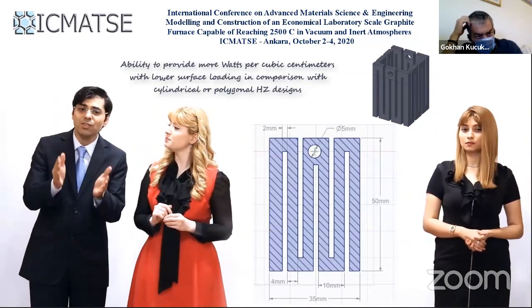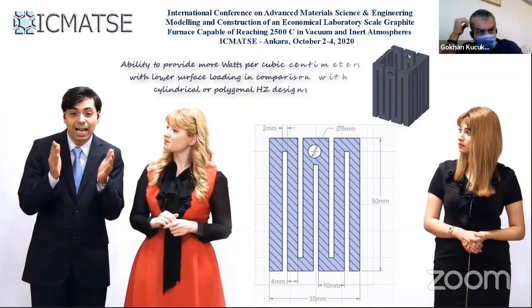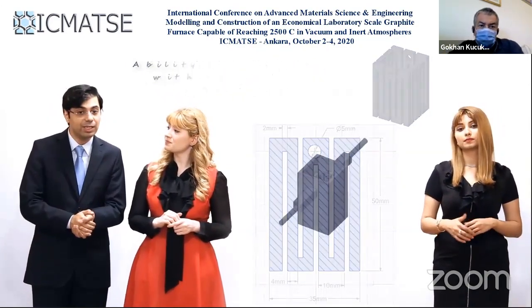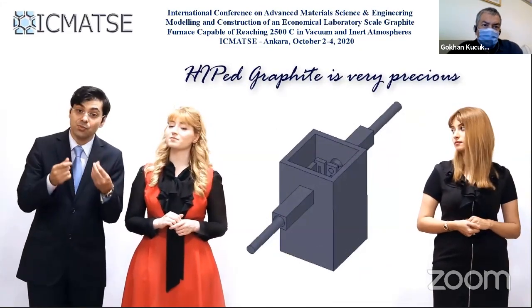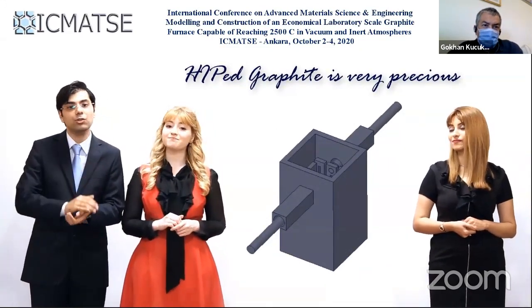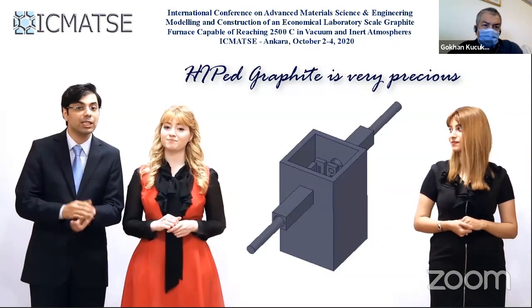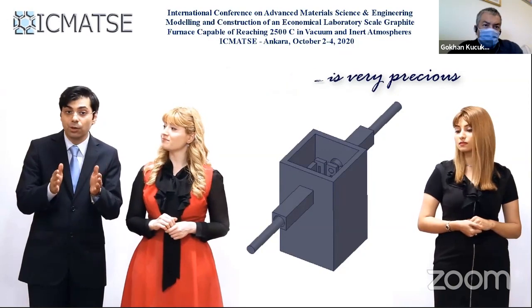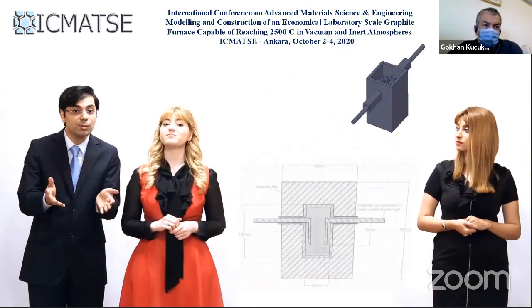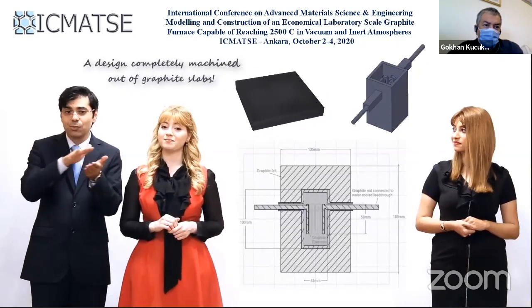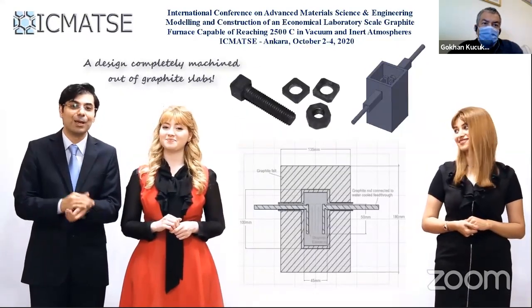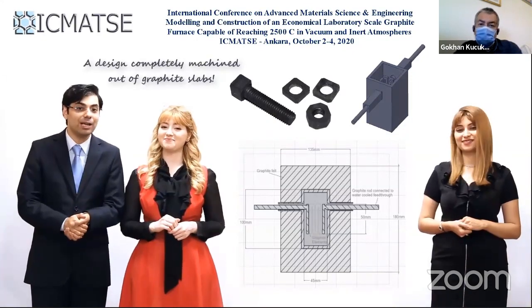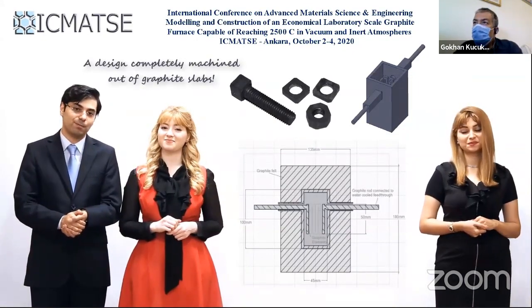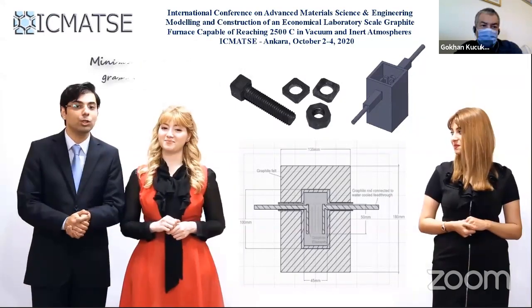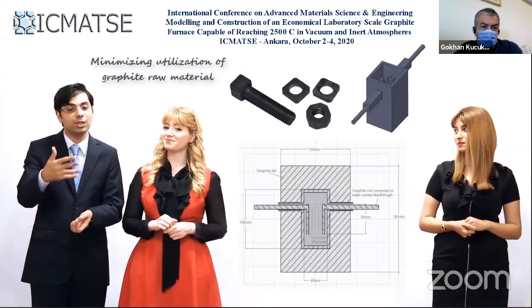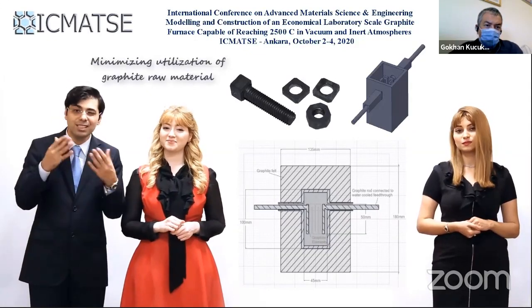Moreover, every cubic centimeter of high-purity graphite which has been sintered at elevated temperatures using hot isostatic press technology is very precious. So it is only logical to minimize the consumed graphite during machining of the geometry required. Therefore, in the proposed design, it is possible to simply machine slabs of graphite and to connect them using nuts and bolts made from the same grade of graphite, minimizing the wastage during the manufacturing process. It is also noteworthy that a similar volume of hot zone constructed in the conventional cylindrical or polygonal design consumes a significantly greater amount of raw material.